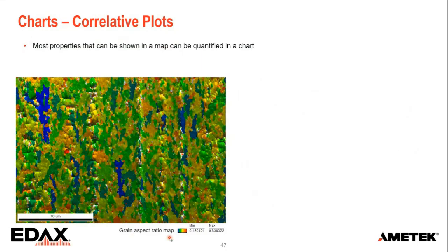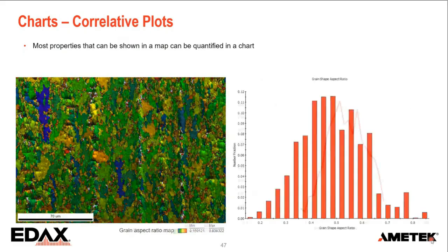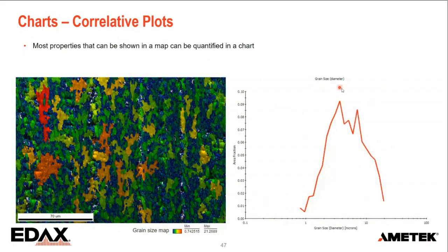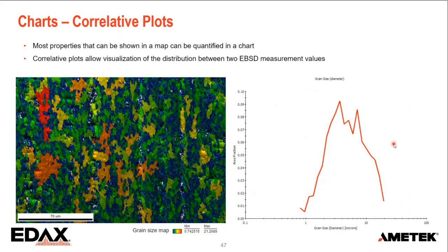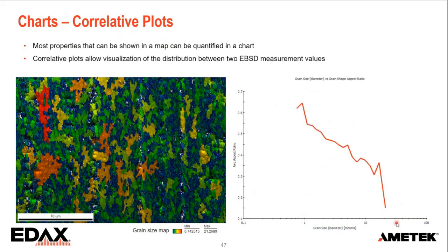Now, we can go one step further. This is another material grain shape aspect ratio map. We can quantify that, but we can also compare that with the grain size. So here's the grain size map. In color coding, in black, you can just see the ellipses. There we have the grain size distribution. And we can then mix those two and plot them against each other. So you can see how the grain shape scales with another feature like the grain size. And this is available for many of the parameters that we can apply.